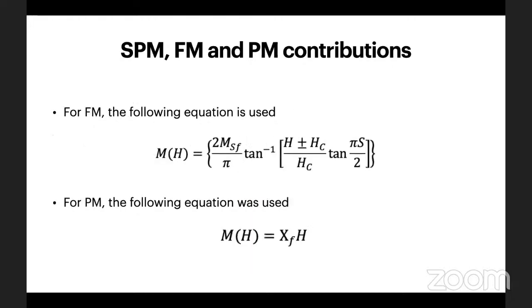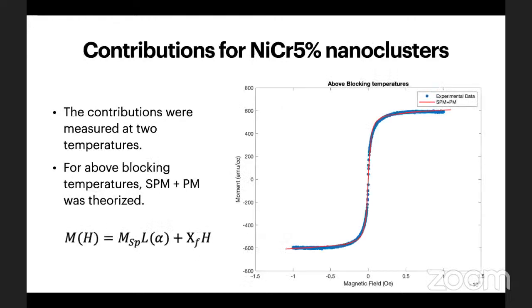Then for FM, we have made use of the following equation, and for PM, we made use of this simple linear equation. So here I'm showcasing MH fittings only for one sample, nickel chromium 5% nanocluster, since I don't have much time. According to theory, SPM would likely contribute more for data above the blocking temperatures. But to increase accuracy in our study, we added PM contribution as well. The following SPM plus PM equation was used, and this resulted in a good fit that is showcased on the right.